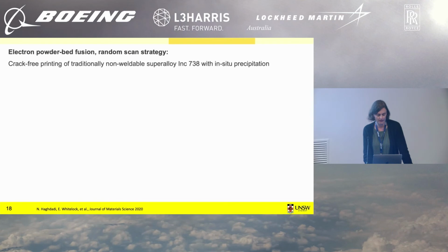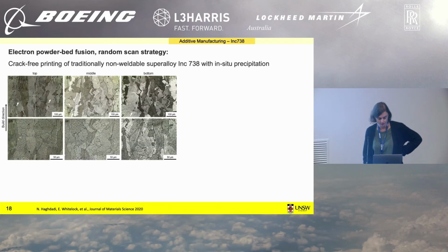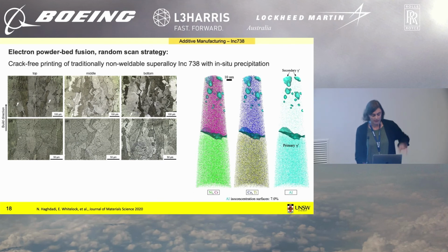Last quick example, this is for electron powder bed fusion, and we are very excited about that because the electron beam allows us to do very different and new scanning strategies. So in this case, we used a so-called random scan generator, which just fills random points. And this enabled us to print a traditionally non-weldable nickel-based superalloy, Inconel 738, crack-free. So you just got to believe me based on these micrographs here. And at the same time, without doing any additional thermal treatment, because this is done at slightly elevated powder bed temperatures, we achieved a nanoscale in situ precipitation of particles that we wanted to have.